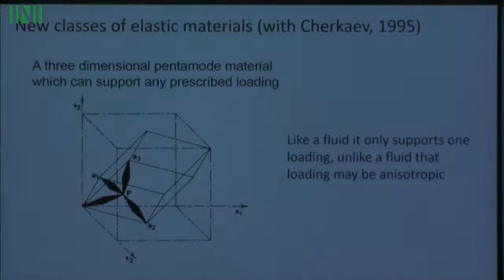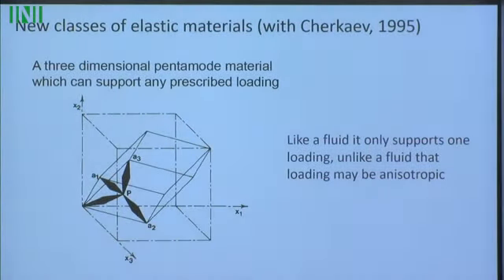So another interesting metamaterial, a new class of elastic material, and this is joint work with Andrej Cherkaev in 1995. We were looking for a structure which is a little bit like water, in that water only supports one loading, namely a hydrostatic loading, but we were after structures that could support anisotropic loadings as well, for which the elasticity tensor is essentially a rank 1 tensor. And so this is a unit cell here.